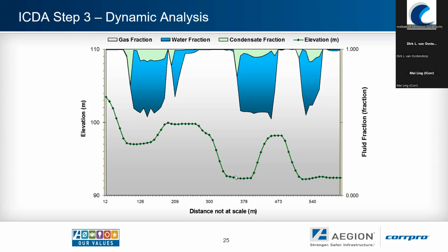Moving over to the area between 350 and 378 meters, you would normally think that in a low point, that's where the highest accumulation of water is going to be. But in this particular case, that wasn't true. It was actually on the uphill portion of that next pipeline rise. And then there was carryover, which allowed water to deposit on the downslope side at around 540. So this is where the composition tracking became very helpful.